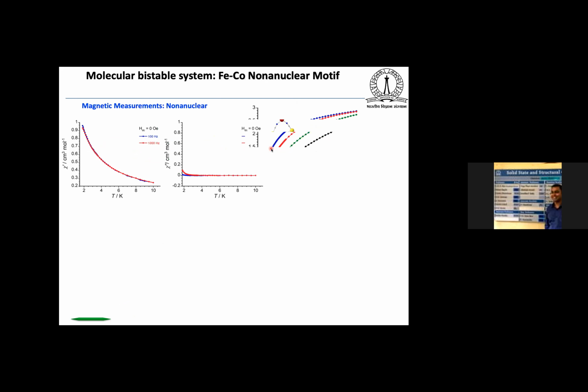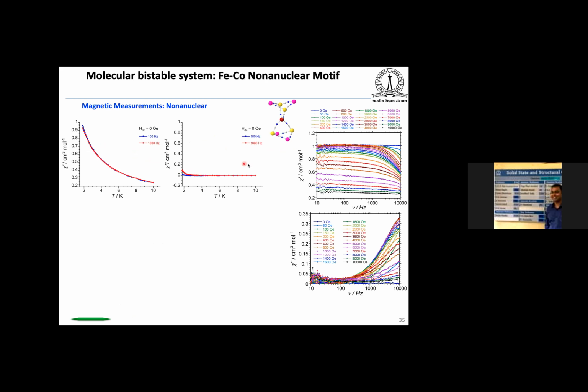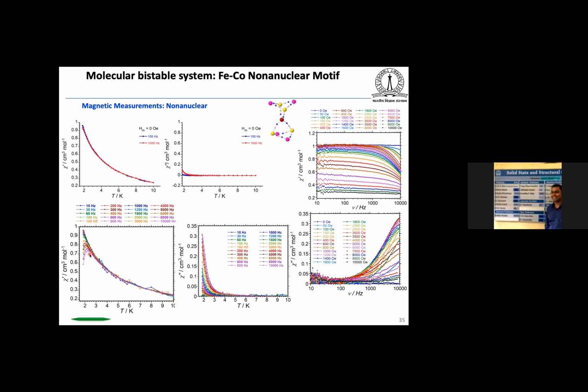And what we have observed, when you measure under 0 Oe, is a small maximum coming out in the χ second prime. Using an external DC magnetic field, you can see in the χ prime and χ second prime versus T that there is a small maximum coming out. So that is a signature of single molecule magnet behavior coming from this cobalt high spin unit.